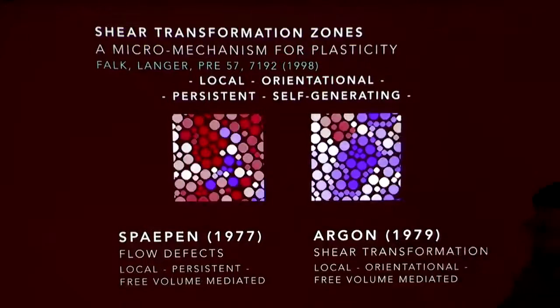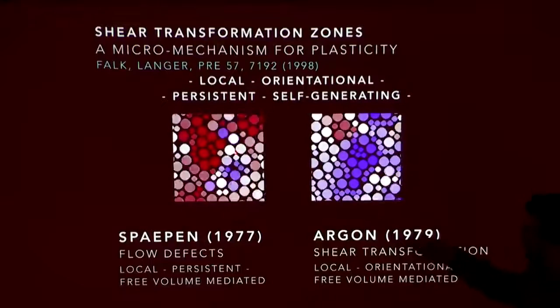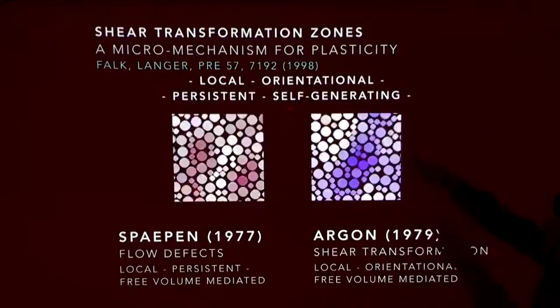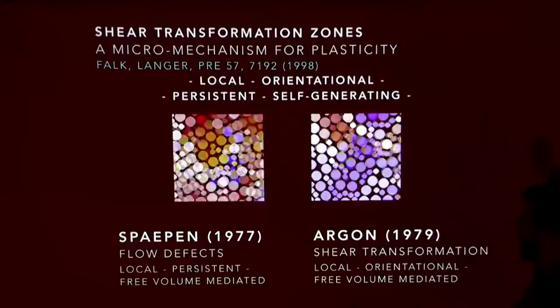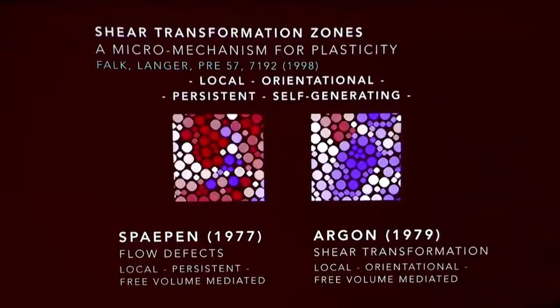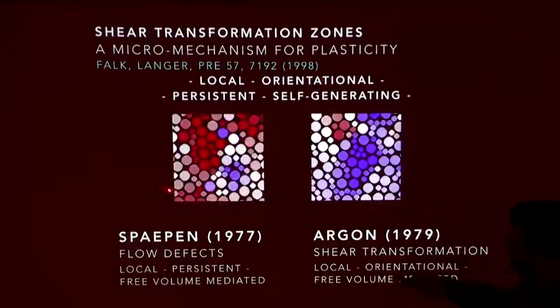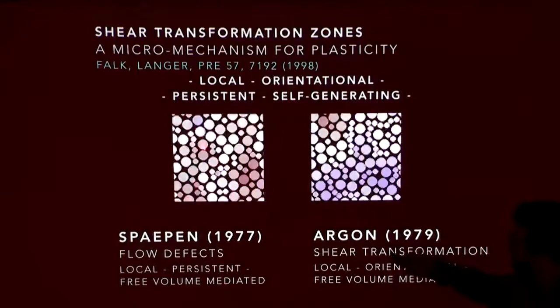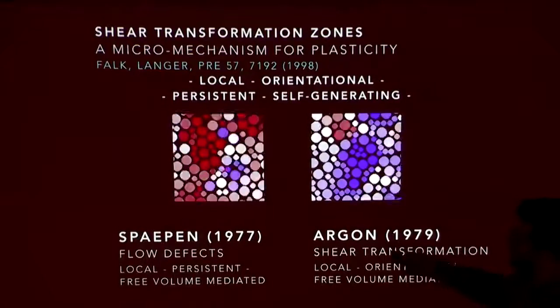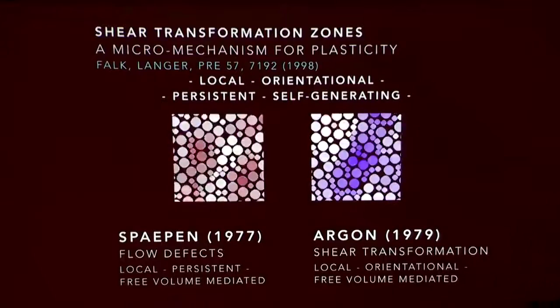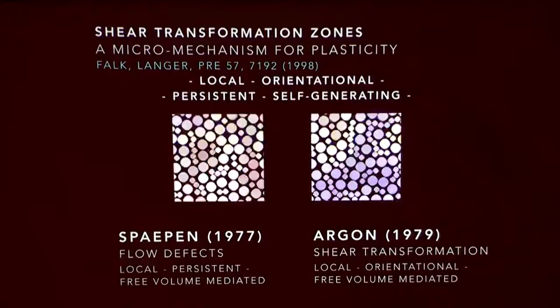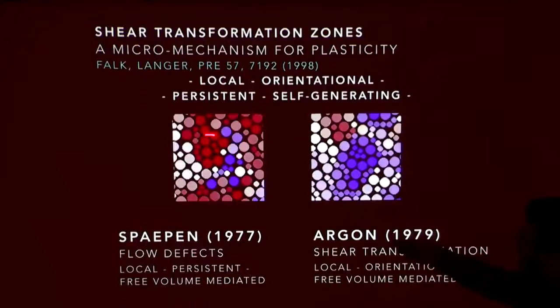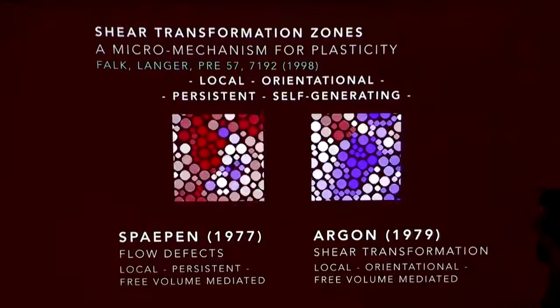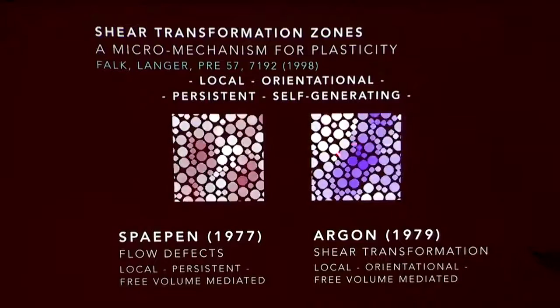And you can see, if you look in the glass, that there are regions where, here, this is a small close-up of a larger sample of a 2D binary glass being loaded, in this case being compressed along this axis and extended along this axis. You can see there's one sort of cage of large atoms surrounding a bunch of small atoms that collapses in just that way. So you can get small local regions of the glass that undergo mechanical collapses that lead to irreversible deformation. And here's another one from a different region.